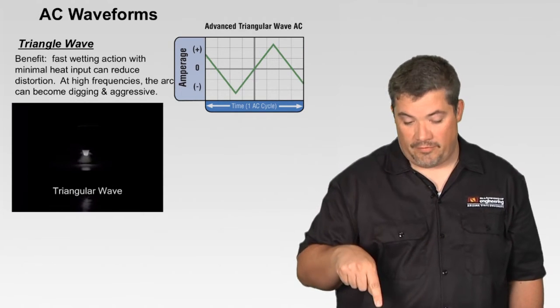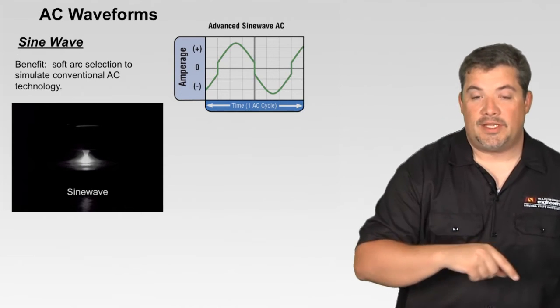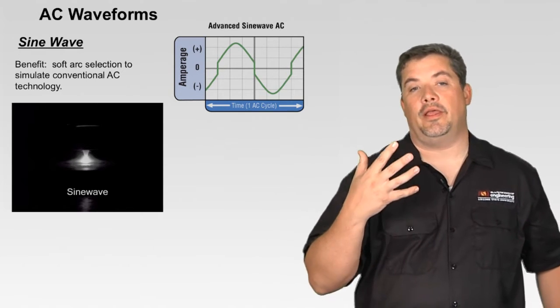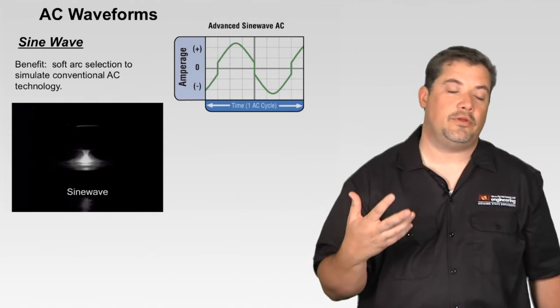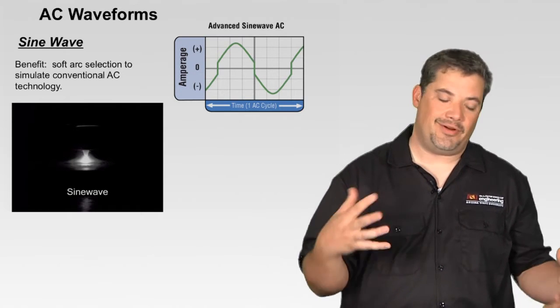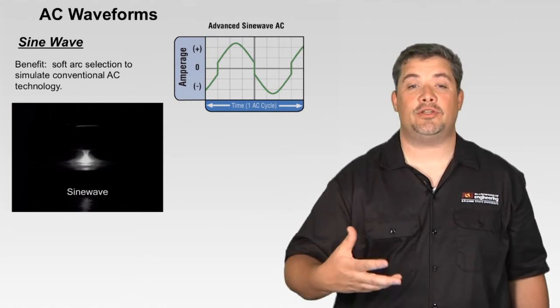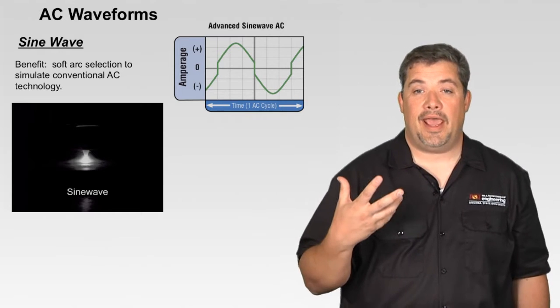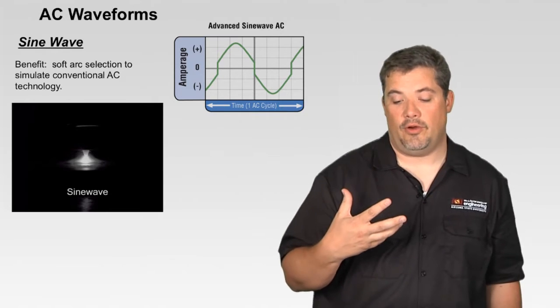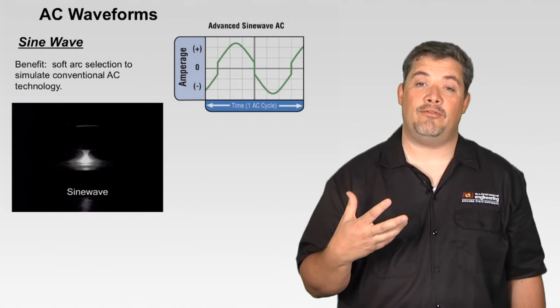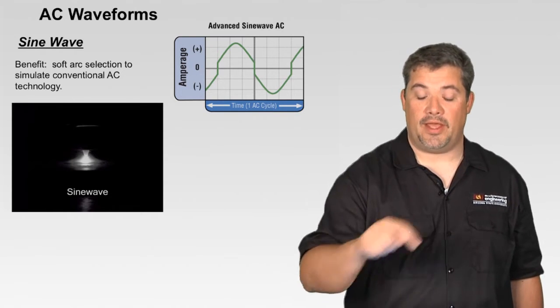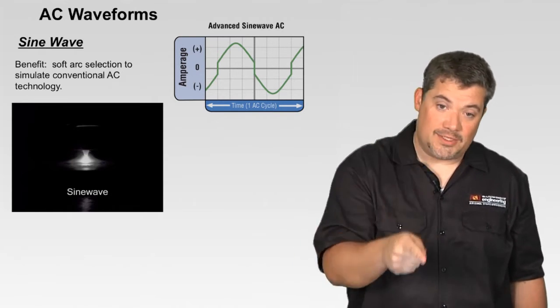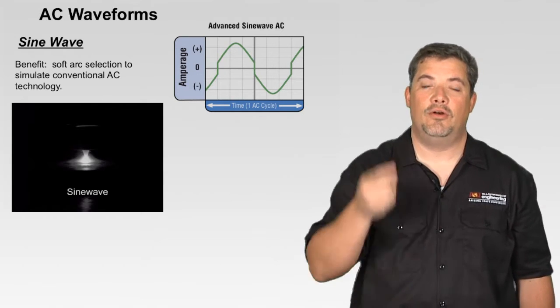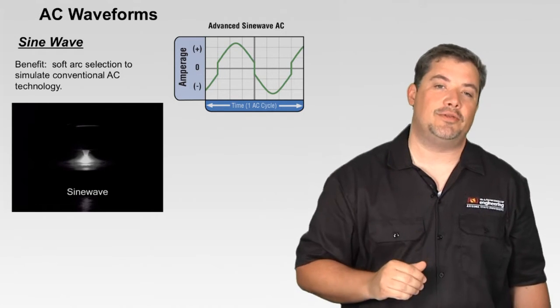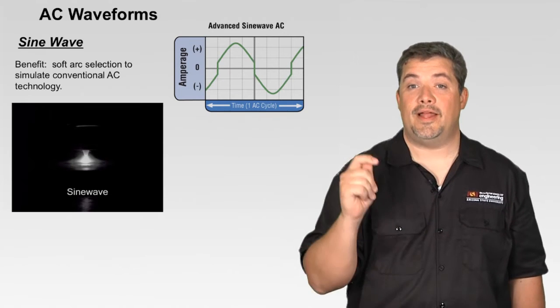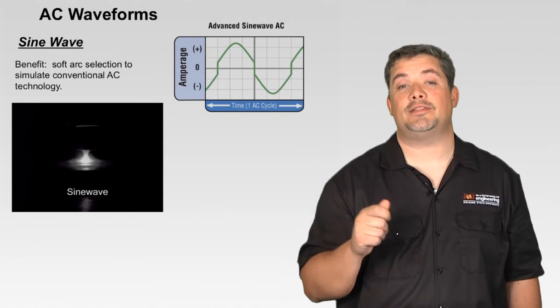So, backing up to the sine wave, the benefit of the sine wave is it's a soft arc. It simulates old school conventional AC welds. It's very soft, it's sluggish, it's not as efficient. You're going to put more heat on the tungsten, and you can see in this waveform design though, it's not a true sine wave, because we have to trick it a little bit in that zero transition so that it almost instantly makes its transition through zero so that it reignites without having to use high frequency all the time. That's the benefit of these new machines, these advanced machines.